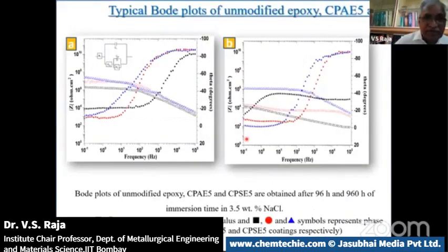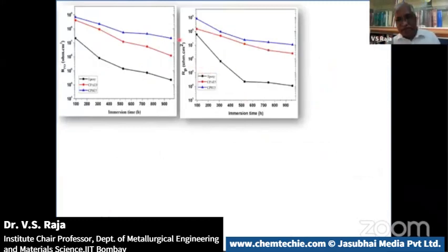I'll show you some of the data that we have got from this. Again, you can see how by modifying this, in systematic work, various proportions of these additives are added, and then the corrosion resistance is determined. These are the plots of unmodified epoxies and epoxies modified with these two additives. Please look, this is after about 1,000 hours of exposure. After about 1,000 hours of exposure, you still have 10 power 6 impedance. That means it's really good. The performance is certainly very good, no problem, in terms of corrosion resistance. And again, this summarizes the data that you see here.